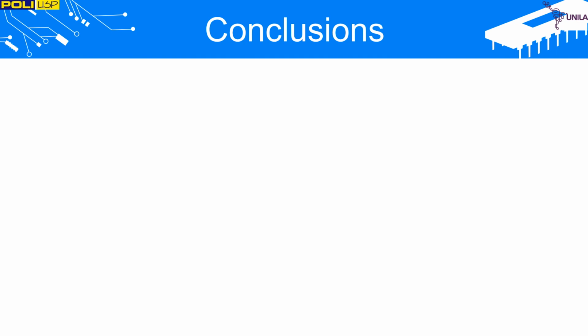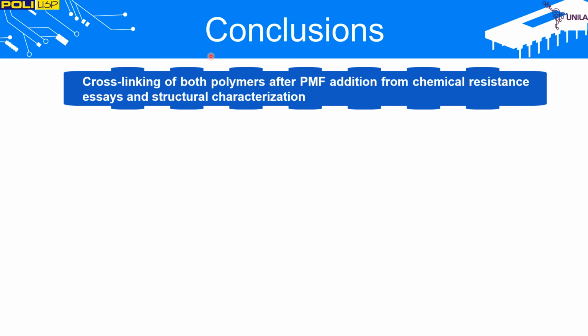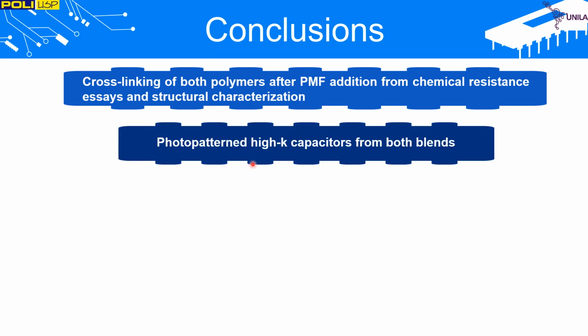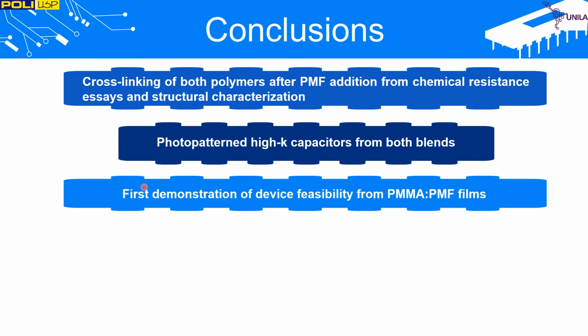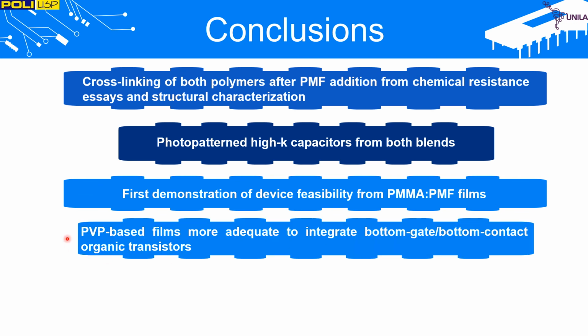Okay, so now the final conclusions. Cross-linking of both polymers was verified from chemical resistance assays and structural characterization. Photopatterned high-K capacitors from both blends were demonstrated. It was the first demonstration of device feasibility from PMMA with PMF films. Despite that, PVP-based films were considered more adequate to integrate bottom-gate/bottom-contact organic transistors.